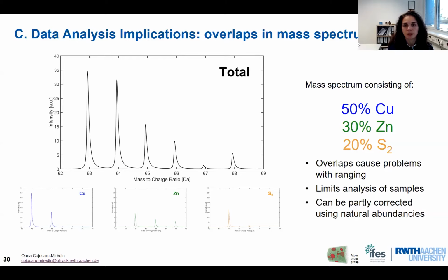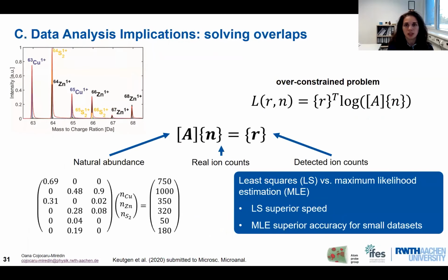So these peak overlaps definitely hinder us from having a reliable compositional value at the interface. So it hindered us from being quantitative. And the good thing is that we can resolve this peak overlap using natural abundances. And this is what we have done in the work that we submitted recently to the Journal of Microscopy and Microanalysis, where we used the natural abundances to resolve the peak overlap between copper, zinc, and sulfur-2